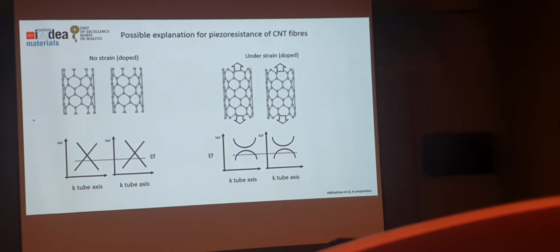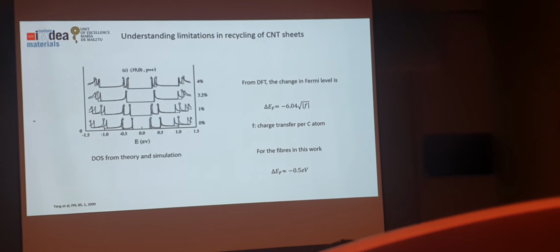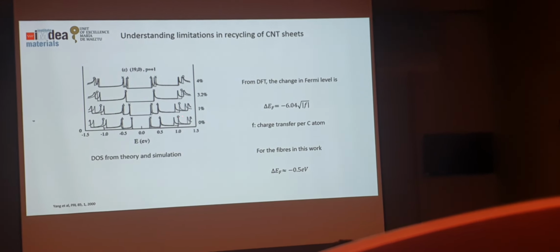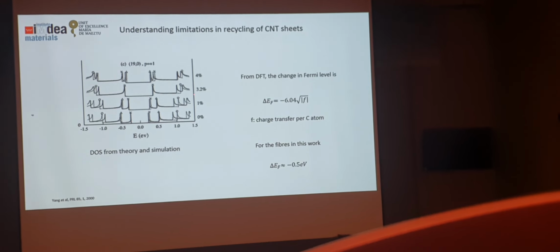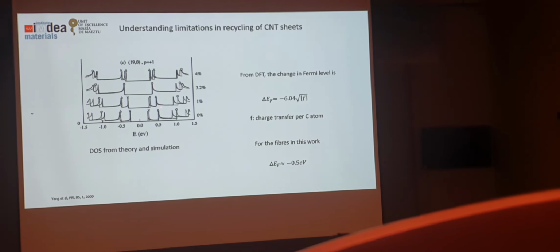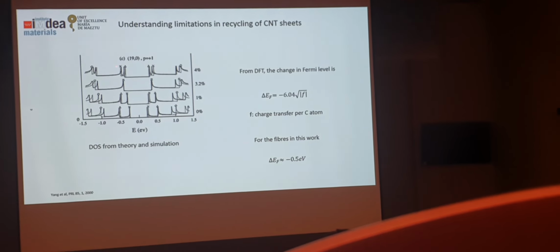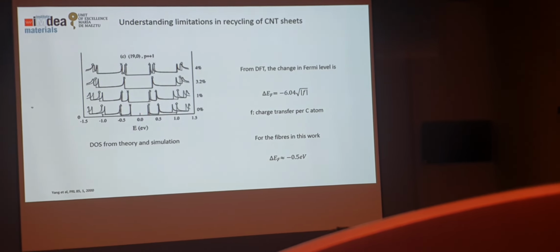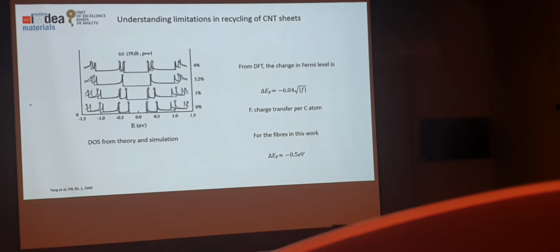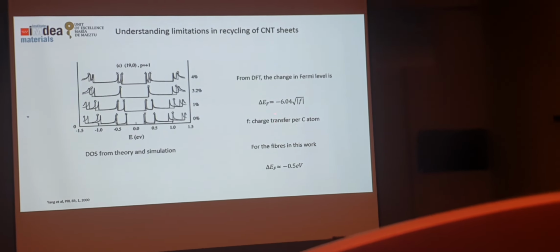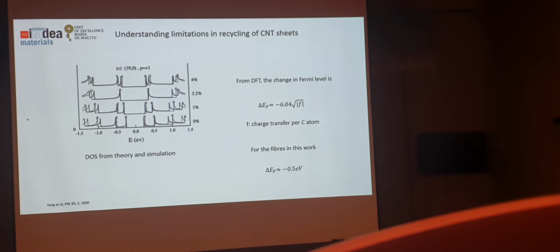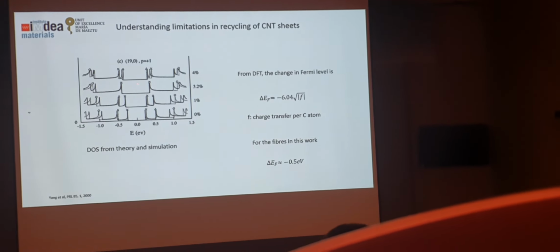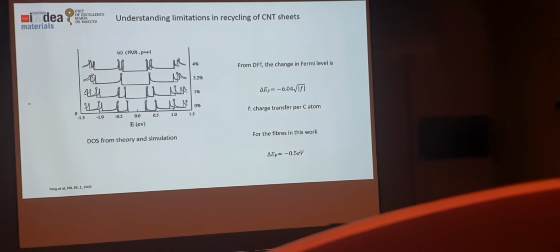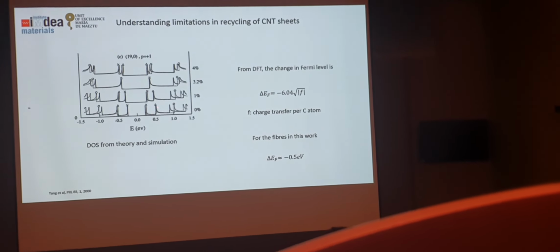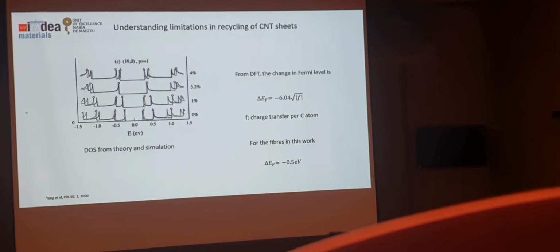Now, of course, when we produce cartoons like this, it's always good to compare with something more real. So this is the simulation that others have done for the effect of strain on individual tubes, and you can see that, for instance, if you stretch them, say 4% to 3%, you do get these really large changes in the density of states. And the question is, how do they compare to the kind of doping we find? For the these fibres we've been doping, we typically see Fermi level changes of about 0.5 electron volts. So it is possible that the Fermi level is somewhere here where strain is inducing huge changes in the density of states.